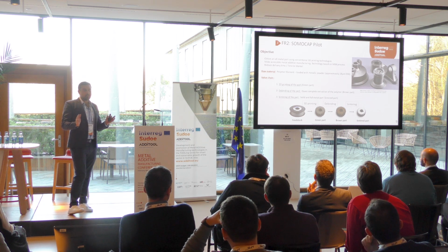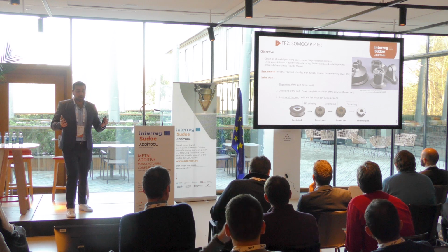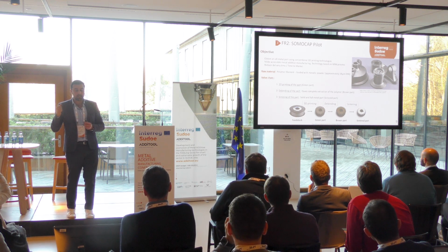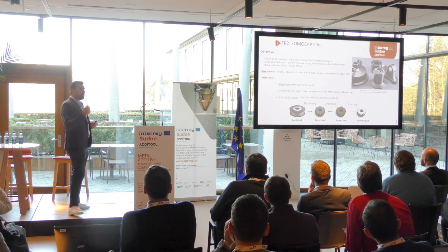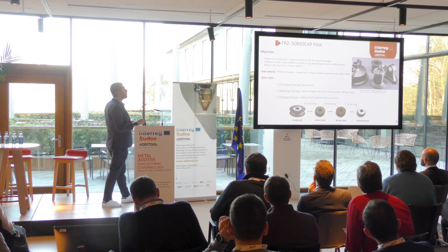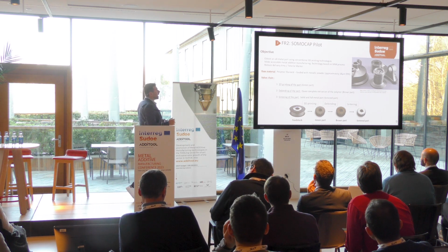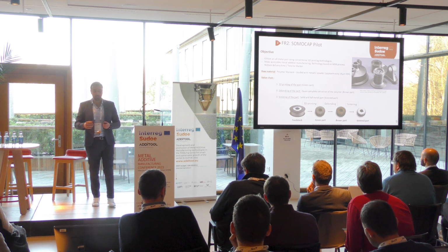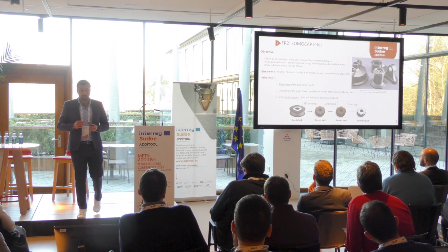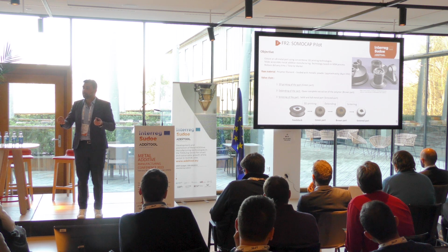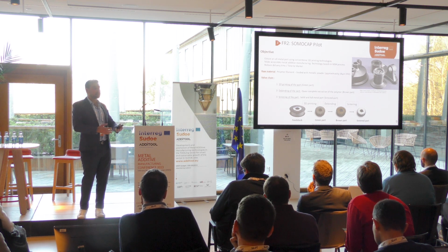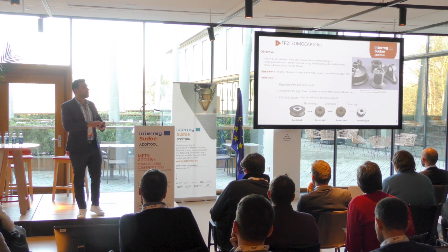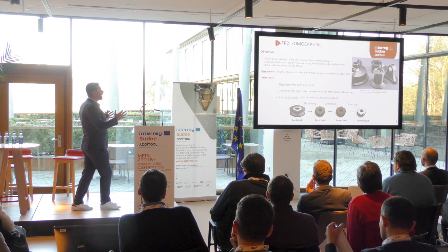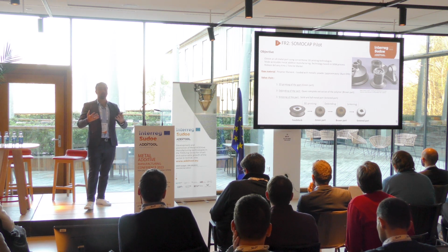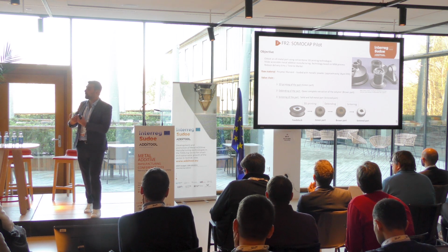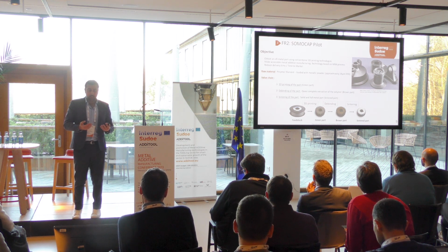The raw material here is a polymer filament, the feedstock. This polymer filament is loaded with a metallic powder, and we have approximately 18 microns D90 inside the polymer. So we print the part, then we have to debind it, extracting quasi totally the polymer. At the end of the debinding process we call it the brown part.